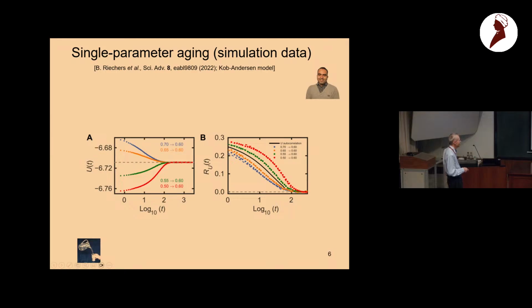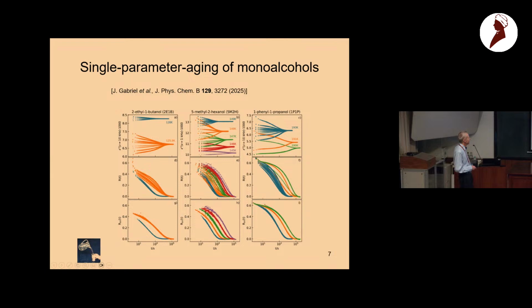These are the normalized relaxation functions as a function of log time. The fortunate thing with computer simulations is that we can use the fluctuation dissipation theorem, so we don't have to measure the linear response. We can just calculate it from the potential energy time autocorrelation function. So we know the linear response, which is the black curve, and from that we can predict the other ones. The dashed colored curves are the predictions, and it seems to work okay.